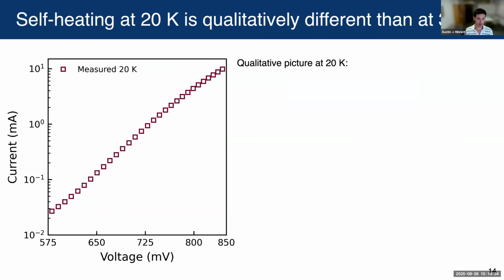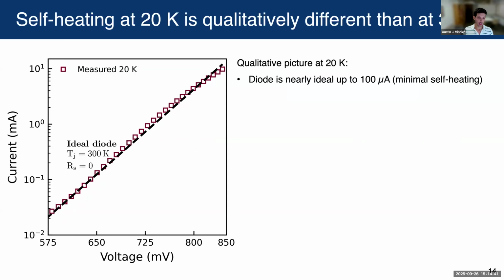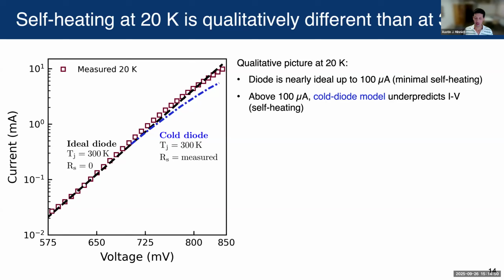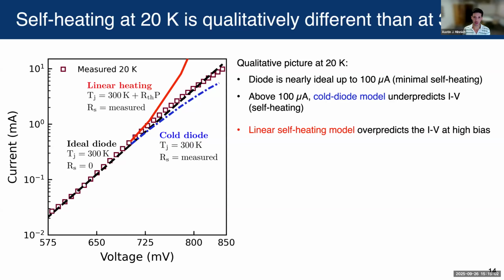Now at cryogenic temperatures, the story is a bit different. So these are now 20 Kelvin IV characteristics. We can see now the region of ideality is quite a bit less, so only up to maybe 100 microamps. If we put back in series resistance, we again significantly underpredict the measurements. But now the interesting thing is if we put back in self-heating with a constant thermal resistance, we get this red line, which doesn't look anything like the data.